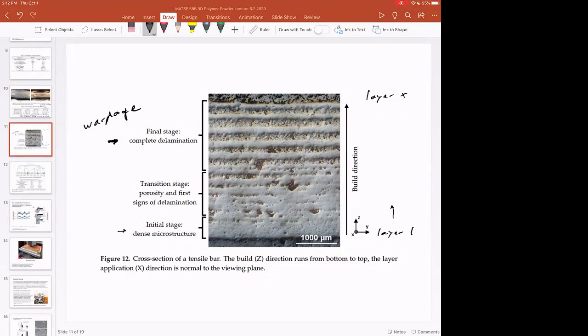And so this is something that has to be examined, and this is something that you have to think about when you set up your build profile, is if you get too much coalescence at the bottom down here, you can get really significant delamination issues later on in the build as you build the part thicker and thicker and thicker. So this is 1,000 microns, so this build is on the order of 4 millimeters or so. And so if you get too much coalescence of the powder, this can happen. So that's just one nice example and something to think about in these types of builds. Any questions on that?